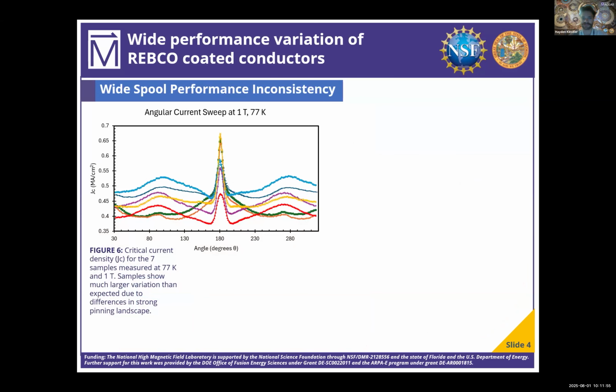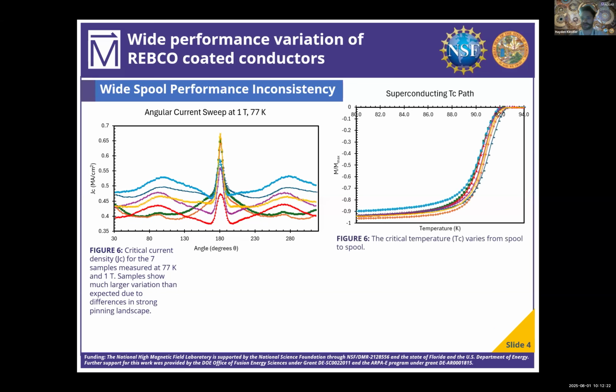We found that at 1 Tesla and 77 Kelvin, there is quite a bit of variation between spools. Each of these lines is a different spool, and specifically the peaks around 90 and 270 degrees are due to strong pinning forces within the REBCO to pin the vortices. And because of this variation, we see that there are different pinning forces within the spools. Similarly, with the critical temperature, we found that there is a wide variation of the onset temperature. So the onset temperature is where the material starts to lose its superconductivity, and between the 7 spools, it ranged from 80 to 87 Kelvin.